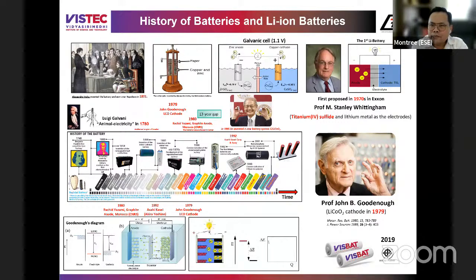In the old days, people used lead acid, right? And after that, in the 1970s, Professor Stanley Whittingham was the first person who used titanium disulfide at the cathode, right? And using lithium metal at the anode, right? Lithium metal loves to give electron, right? It's quite an active element. And then it oxidizes, becomes lithium ion, and electron goes to the cathode side. And lithium intercalates into titanium sulfide, because this material is a layered material, but it's not so stable. So anything based on sulfide compound easily generates hydrogen sulfide and so on. So sulfide is not stable.